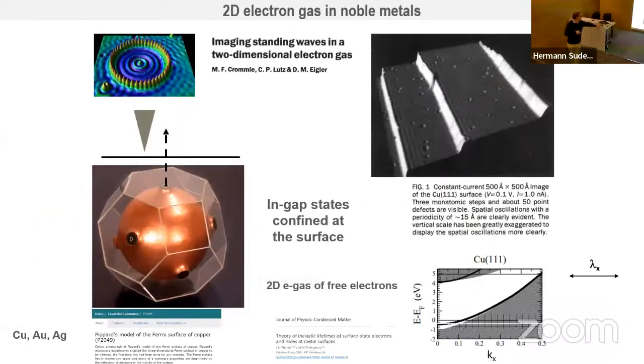Now, you may do this in copper. You can get a lot of electrons in copper, but there are places where the Bragg scattering opens gaps, and there you can find such a nice surface state, which you can follow and see by the ripples which have been seen using STM.